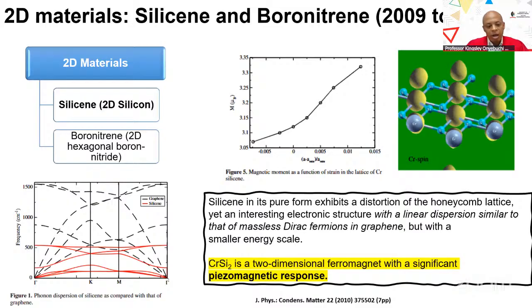We asked, can we evaluate silicene because graphene is a hot material that was recently discovered? And is this stable at first? How do we evaluate the stability? To evaluate the stability of this material, we calculated the phonon frequencies. If you look at the phonon frequency, the red line is silicene and the black line is graphene. In comparison to graphene, you can see that the phonon modes for silicene are actually lower than the phonon modes of graphene. And it tells us one thing. From just looking at this, graphene is actually a harder and stiffer material than silicene. And we've done a lot of work to show this, and a lot of people have worked on this.